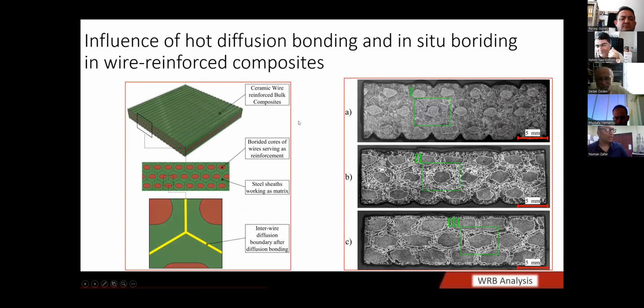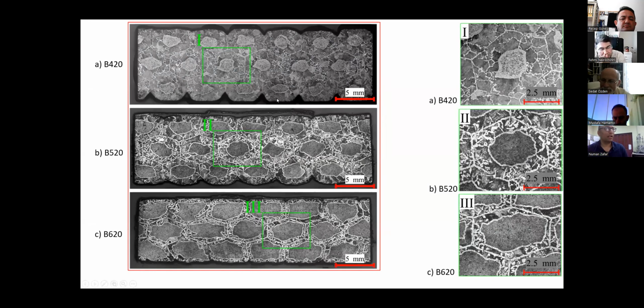Go. Okay. So this is the microstructure of the wire reinforced composites after the treatment. Good news that the wire looks cohesive enough, and we have succeeded in acquiring a microstructure in which sheaths and cores are present, how to say, in peace with each other. These microstructures are enhanced images of the wire cross sections. As you can see, there are no discontinuities, and all those troubles which we have gone through to find appropriate temperature and pressure for the bonding, we have succeeded in increasing the.